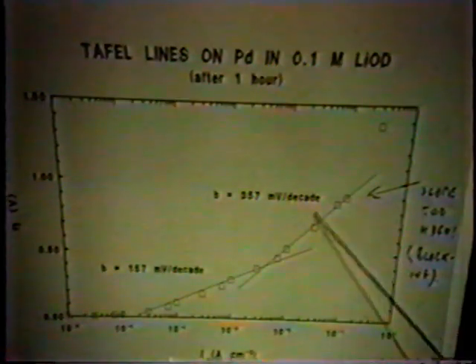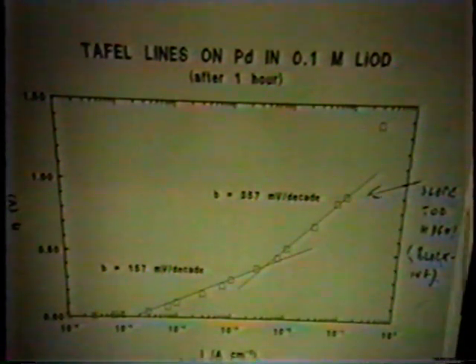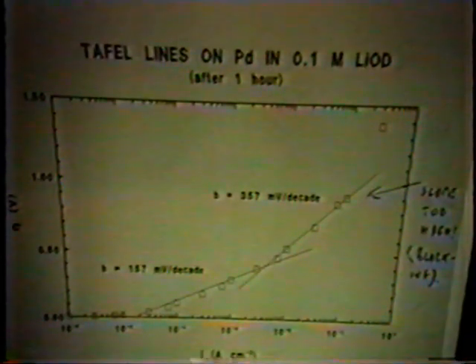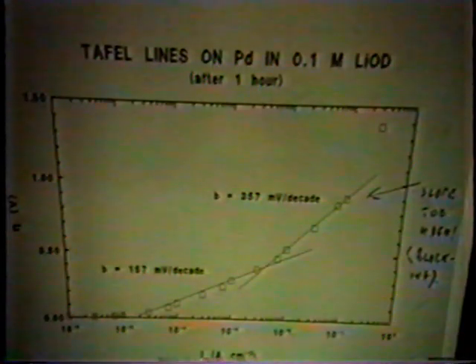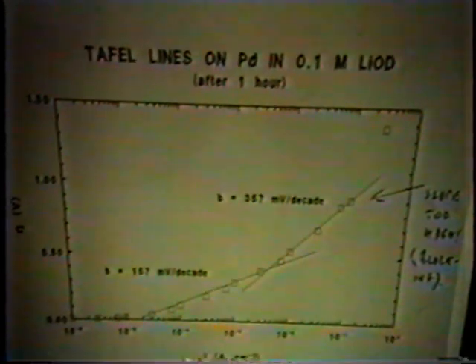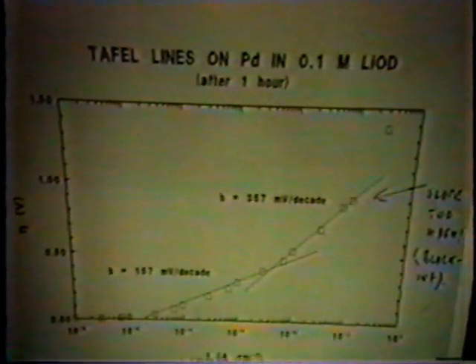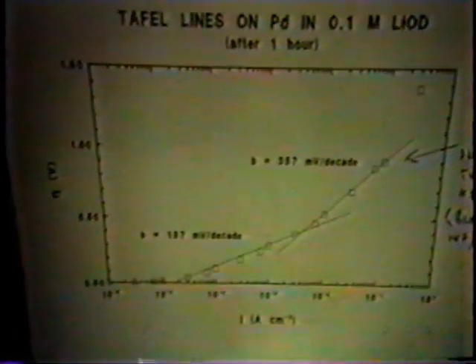And electrochemists, however, for quite a long time now have been explaining very high Tafel slopes you sometimes get as indicating adsorbed material, absorbed impurities on the surface. So when we saw that line, before we did our XPS analysis of the surface that I'm going to show you, we immediately said, aha, that means it's a very dirty surface, and we've got stuff there, which is muck, going to spoil the line. We can even do a calculation about it and show that if the muck has a dipole moment of something like 2 debye, a reasonable dipole moment, then it fits in with the slope of about 330, 340. So we believe that it rationalizes it, it doesn't prove what causes it.